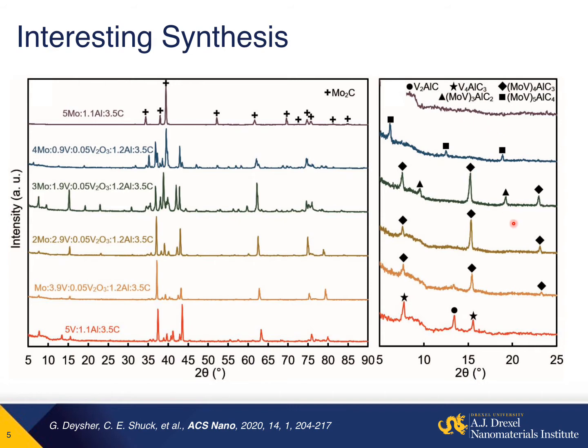So if you look at the M2AX structure, this is the 002 peak for the M3AX2, the M4AX3, and when we did this synthesis, we actually saw the 002 peak for the M5AX4 here, which is significantly farther to the left than any other published MAX phase. Now, moreover, what's interesting is we only saw this when we had the specific chemical composition of 4 molybdenum to 1 vanadium.